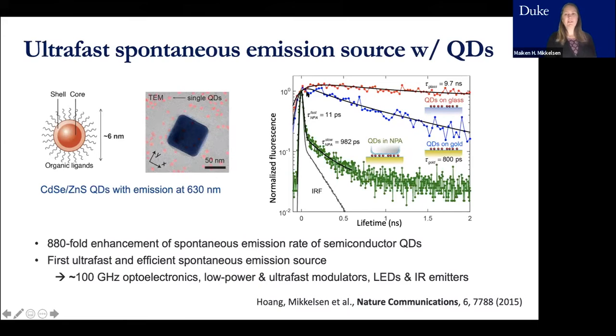These are a very standard emitter that has a lifetime of about 10 nanoseconds and are commercially available. So when we are enhancing these, then we are getting very fast lifetimes indeed. We are seeing similar enhancement, almost 1,000 times, but now we get into an ultra fast spontaneous emission rate of around just 11 picoseconds. So this is really pointing towards very fast optoelectronics on the 100 gigahertz, potentially into the terahertz regime. And there could be low power, ultra fast modulators, fast LEDs.